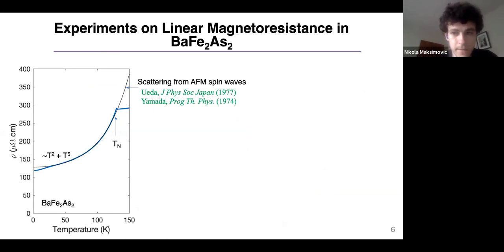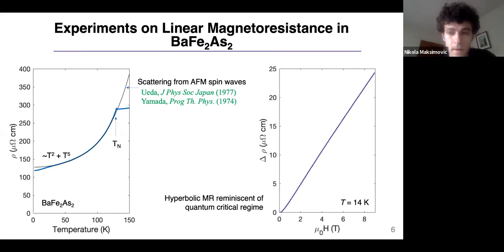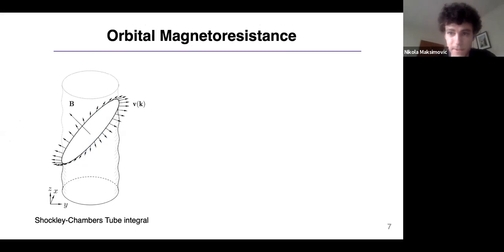So we don't necessarily expect many anomalies in the scattering rate in barium-122, but at low temperature, we see a linear magnetoresistance over an extended field range. And this is reminiscent of what's observed in the quantum critical regime. So this motivates us to look for a mechanism that's based on orbital motion rather than some type of anomalous scattering rate. Okay, so let me describe orbital magnetoresistance and then one simple change that you can make to this model to see H linear magnetoresistance over an extended field range.